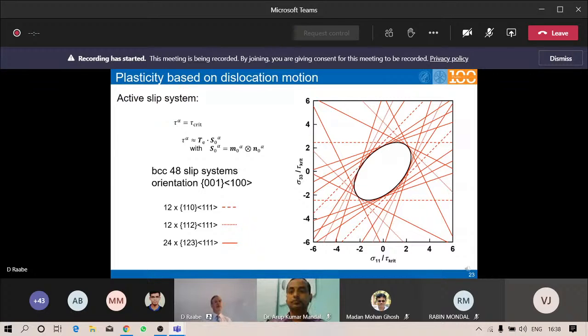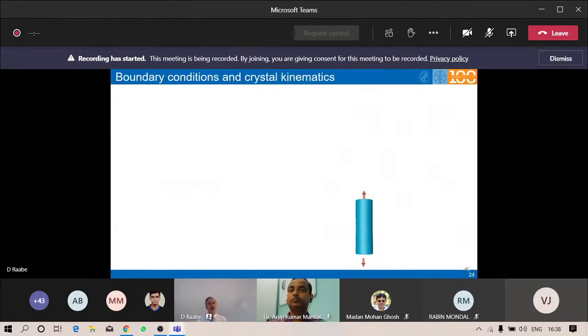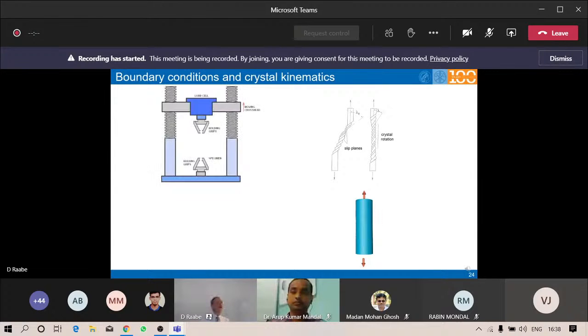Here's a second simple animation from my class, which shows you a single crystal, similar to what we saw before from this textbook picture. And again, everybody knows that you have a certain Schmid factor or Schmid tensor, and you shear the material. But we learned from this very simple picture a couple of things. You see that the crystal is typically deformed under certain constraints. This sounds very trivial, but it cannot move freely as shown in this little animation, but it is tied to these holding grips here in the tensile machine, or it can be due to constraints by the neighboring crystals.